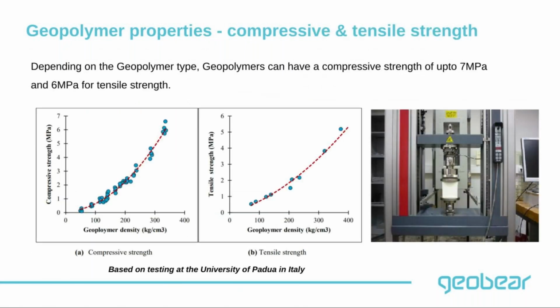Geopolymers have excellent engineering properties, with great compressive strength and tensile strength that can reach up to 7 MPa. So it can resist compression and it can resist tension at the same time, unlike conventional grouting type materials, which are very good at compression but quite weak in tension. Here we've got almost similar properties for both compression and tension.